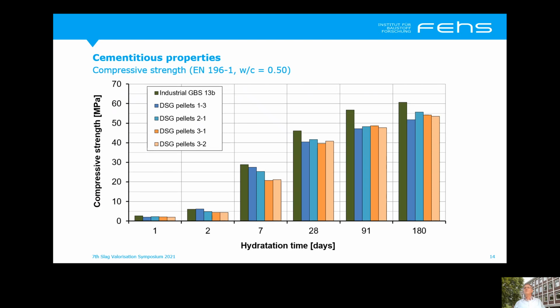First, we look at the compressive strength. The early strength is very low due to the high slag content. Of high interest is that you can see that all strengths from cements made with these DSG pellets are significantly lower compared to the slag cement with industrial GBS.